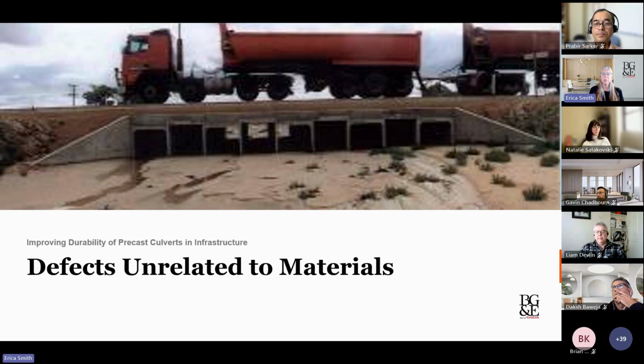During construction, it's important to make sure that you don't overload a structure as you put the backfill in, but also obviously in service. So impact overload at the slab edges, or where you have limited cover, are issues that may affect these precast box culverts. So comparing theoretical load carrying capacity to actual, as well as the failure patterns, is also being looked at by Curtin.